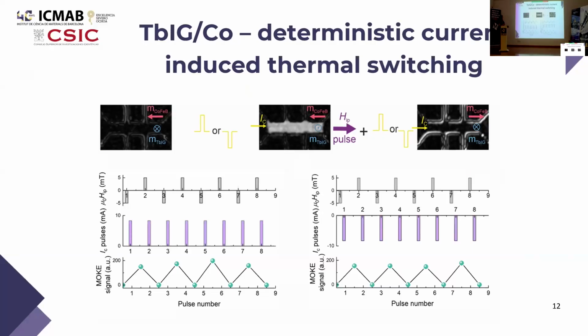So here we have some MOKE images in which we can see that if we set this unfavored state at room temperature, we pass current through the device. It doesn't matter the polarity of the current because our goal is just to induce Joule heating. Then with this, we can switch the magnetization of this out-of-plane layer. And then if we want to switch again, we also have to rotate the magnetization of the in-plane layer because this is the one that determines the state. And as you can see from these figures, this switching is deterministic and is also reproducible over multiple switching cycles.